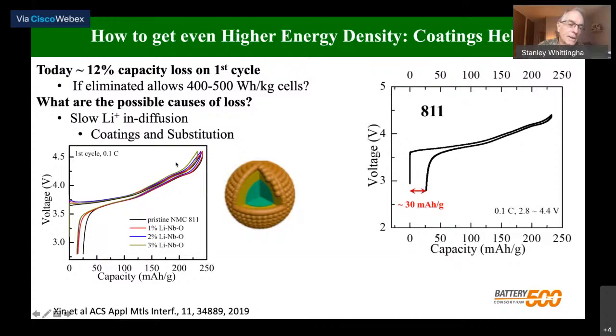So the black one here is the uncoated, unsubstituted, and the others, whether it's 1%, 2%, or 3%, makes no difference. We are recovering some of this first cycle loss. So this coating substitution is helping, and we're looking at a number of newer materials right now which are even better. So this is one solution to this problem, and we hope in the end to eliminate most of this. We won't get rid of it all because we know there's some initial surface reactions.